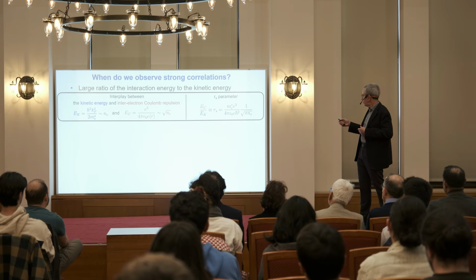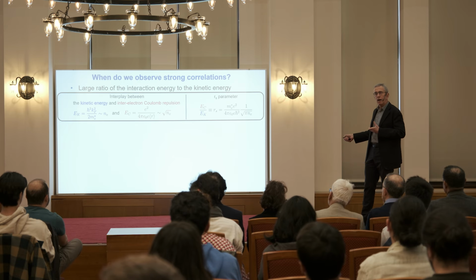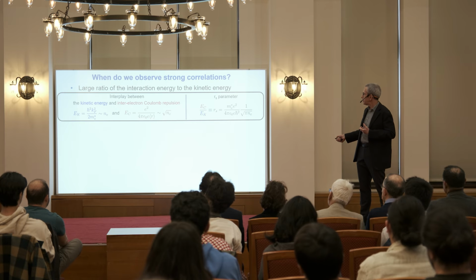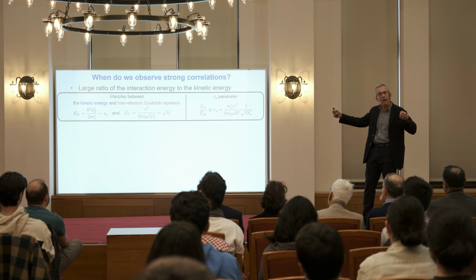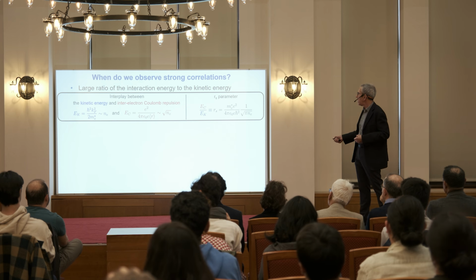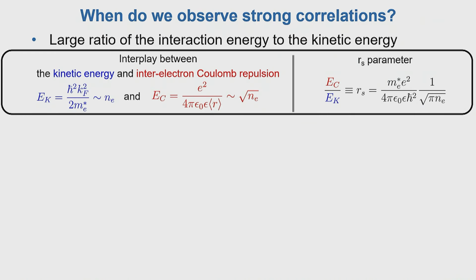principle. Now, the Coulomb interaction is, again, the form you might remember. It goes as 1 over the average distance between the particles, and that scales, therefore, as the square root of the electron density. So the ratio of these characteristic energy scales is the so-called r_s parameter. And it depends on a number of properties. So, for example, the effective mass of the electron is important. And more importantly, it scales with 1 over the square root of electron density.